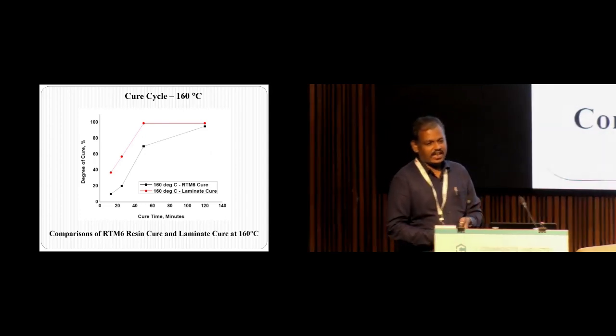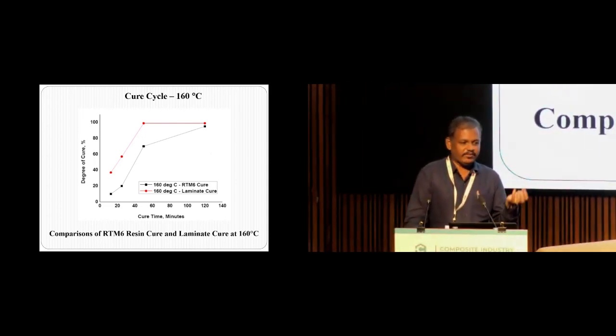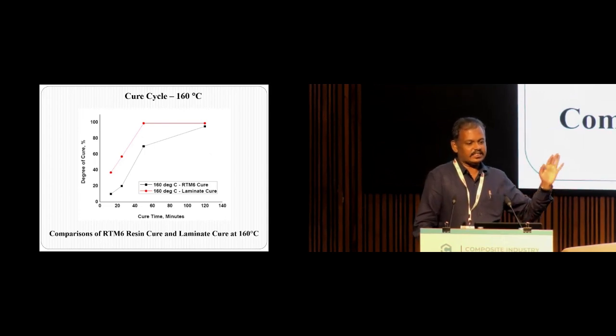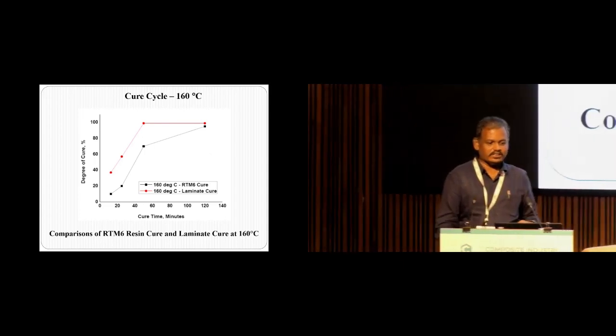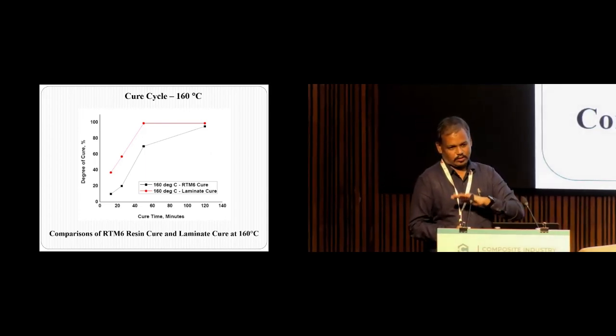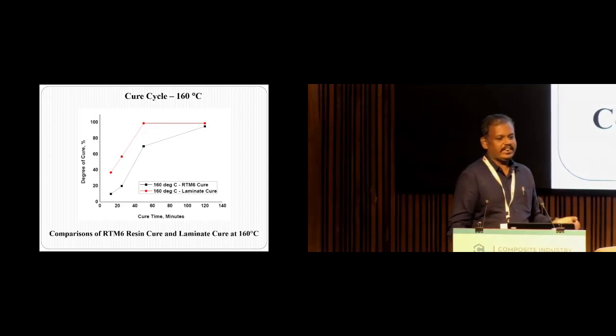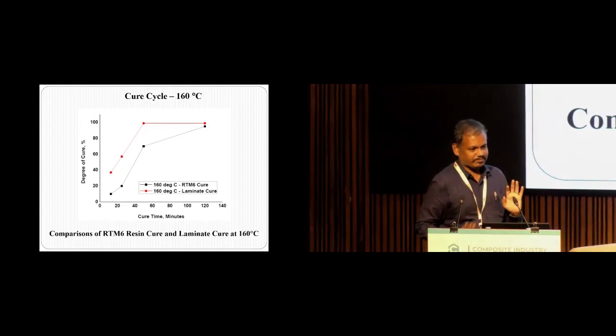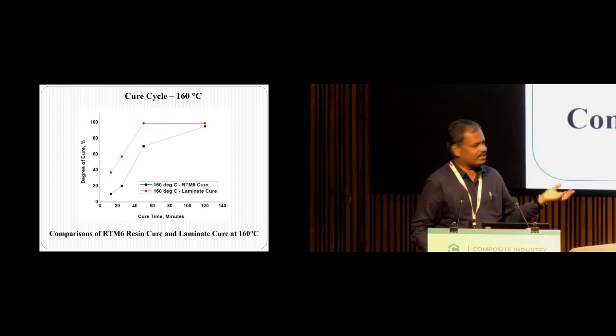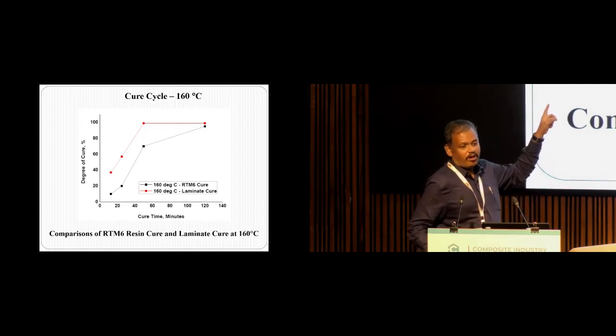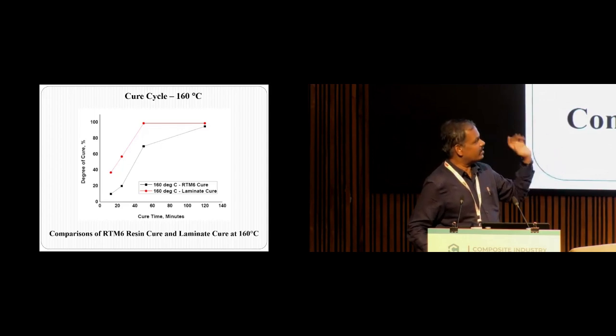When you do resin characterization in DSC, whenever heat gets evolved in the DSC, it is vented out by the nitrogen purge, so no heat gets stored inside the DSC pan. Whereas in compression molding, the sample is completely closed in a metal mold. What happens when the heat gets evolved? It gets trapped inside. Since the reaction is exothermic in nature, when heat is trapped, more heat is evolved and stays inside. Actually, the temperature of the sample is much higher than the applied temperature. That is why the curing of the composite laminate is higher than the resin cure.